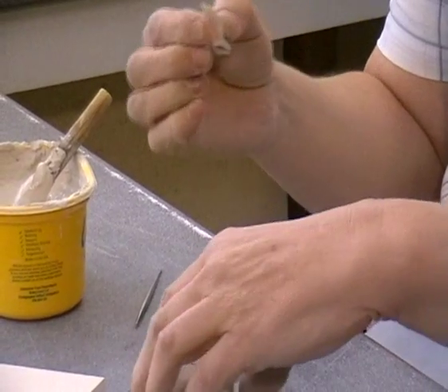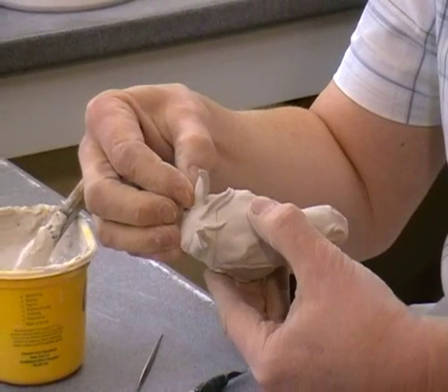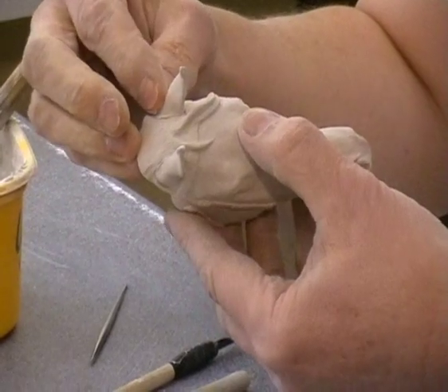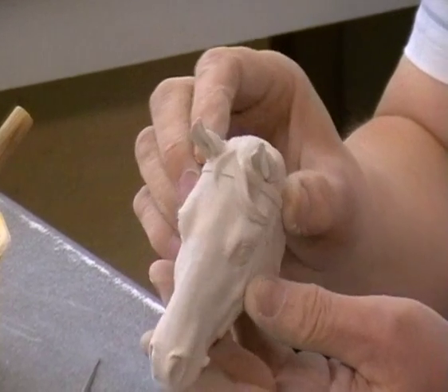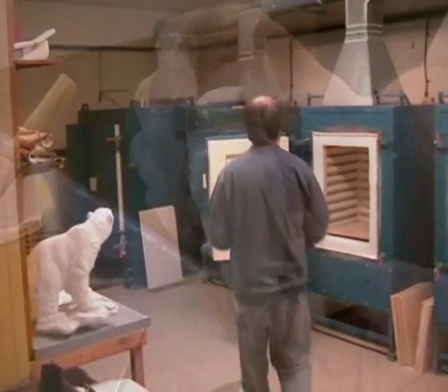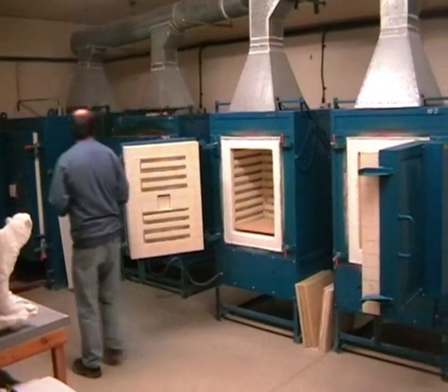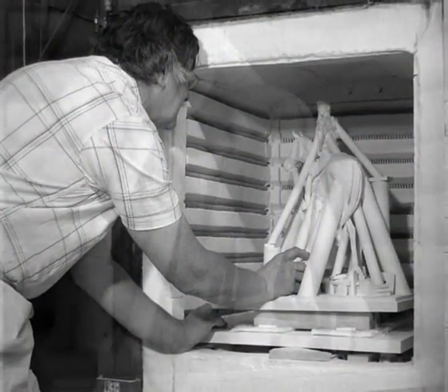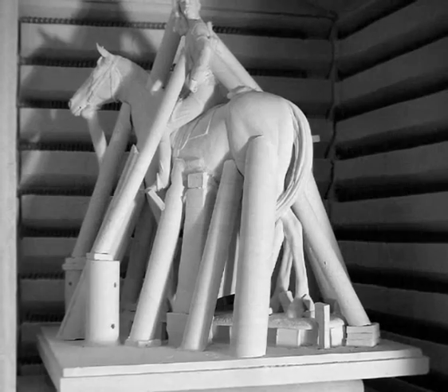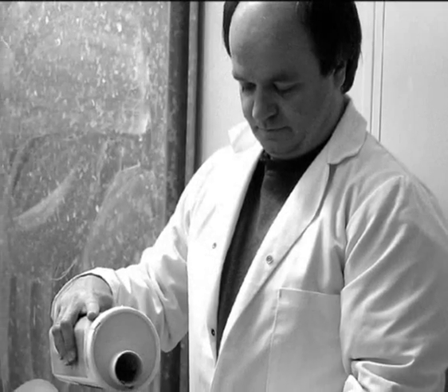This should ensure an accurate rendition of the original sculpture. In order to ensure that the model remains upright during the firing process, a complex series of clay props were then made and fitted. The model, with props, is then allowed to dry out for one month prior to the initial biscuit firing, reaching a peak temperature of 1210 degrees centigrade over a 48-hour cycle.